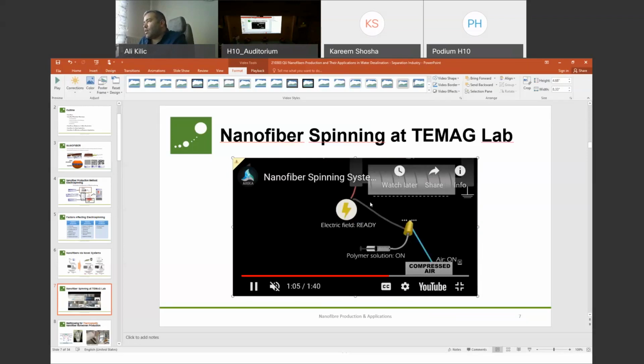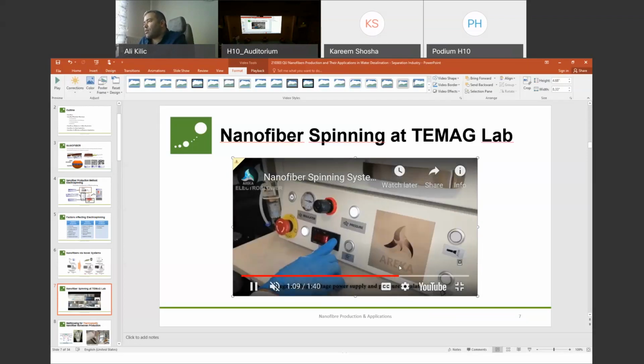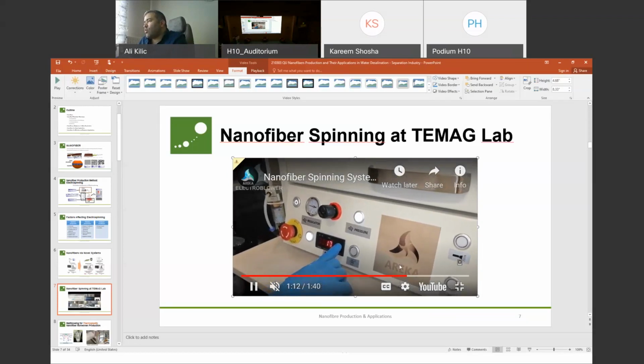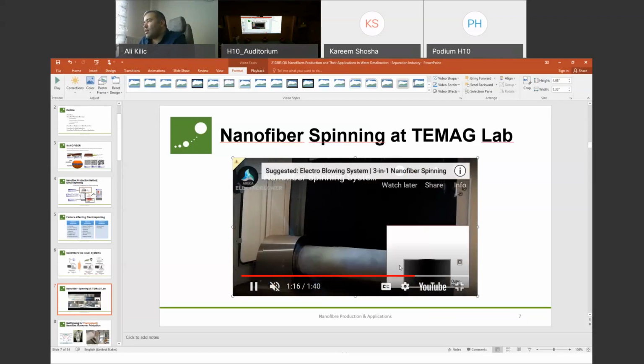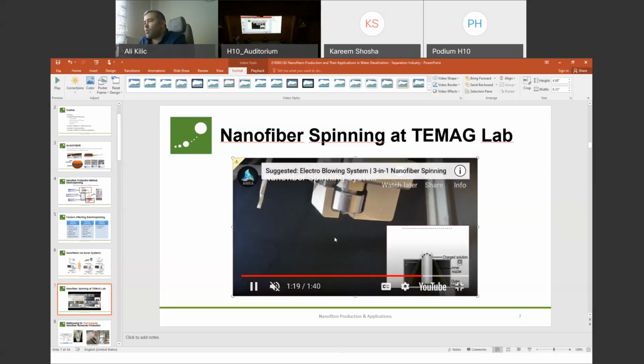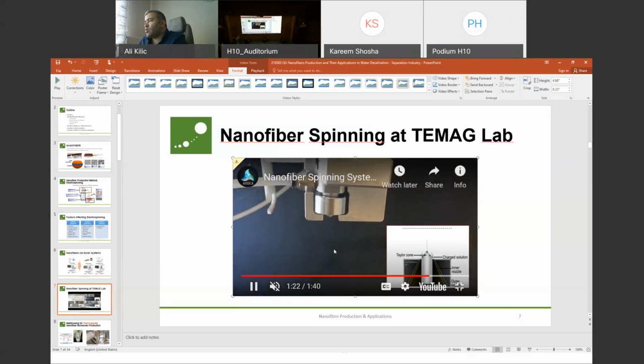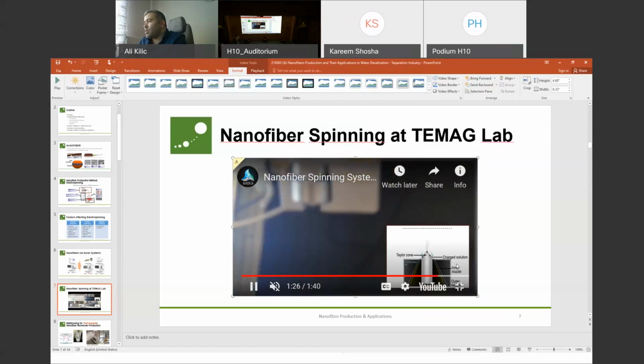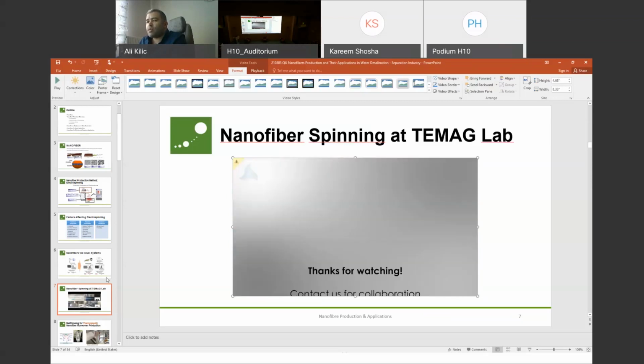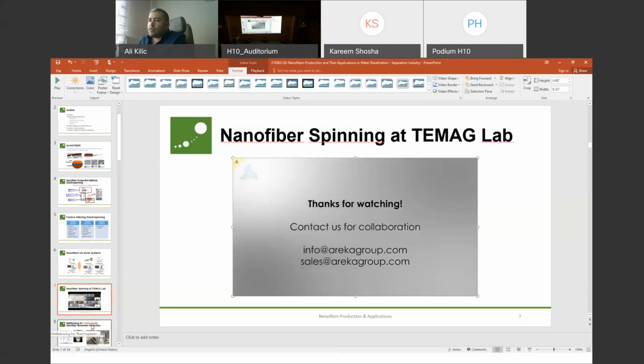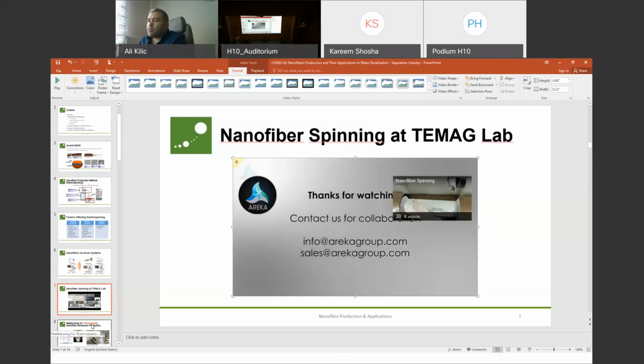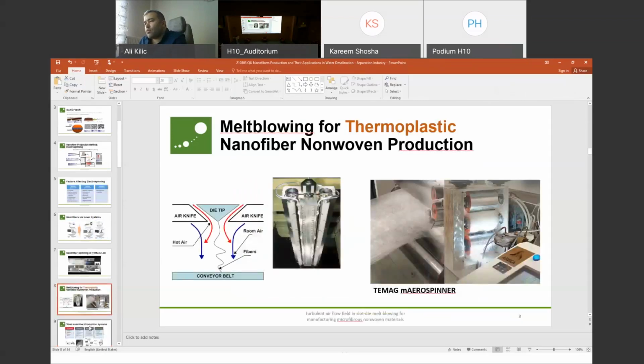And what we did, lastly, is we combined both systems, electrostatics and compressed air, in our latest product. By combining these two forces, we try to enhance the productivity, plus maybe reduce the fiber diameter further below 50 nanometers. As you see here, we are utilizing both compressed air and charging of the system. So these systems are pretty facile and versatile to produce nanofibers and to make them useful for the membrane products that we are using, membrane cartridges used in desalination.